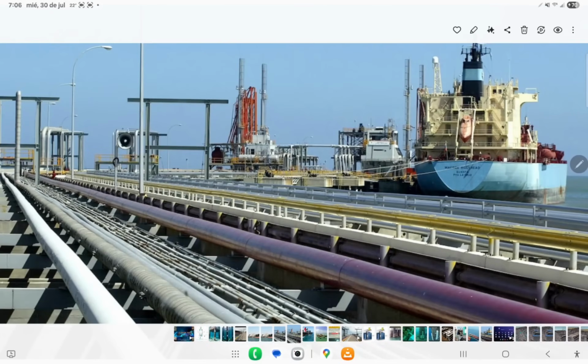The cleaning of the anodes was performed entirely manually, as you can see in this video, where we basically had to remove the coral formation or the marine life that had developed on the submerged piles. Having the entire pile cleaned is not recommended. Remember that the polarization on the piles is due to concentration, and if there is coral formation, it prevents the marine currents from depolarizing the pipe. So I didn't have them clean everything. I was very selective about that because literally, if you remove all the coral formation, that polarization that formed on the substrate, on the layer of the pipe, if the marine current passes through, it will depolarize. So it wasn't convenient.